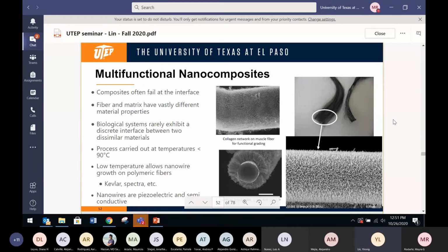Okay, so the other thing we've been working on is doing some chemistry to the fibers, right? As you know, a lot of fibers, especially biofibers, are very rough on the surface. The top left figure you see is a collagen network with muscle fibers. And you see how rough the surface is, right? The rougher the surface, the more interaction the fiber and matrix will have. So that gives you better load transfer capability, right? So what we're trying to do is grow zinc oxide nanowires on the outside surface of a carbon fiber in order to increase its load transfer capability. Next slide.